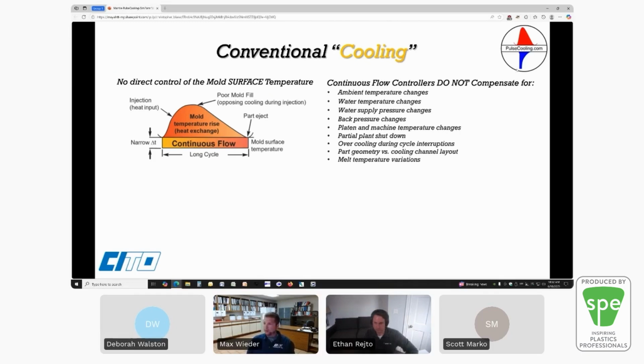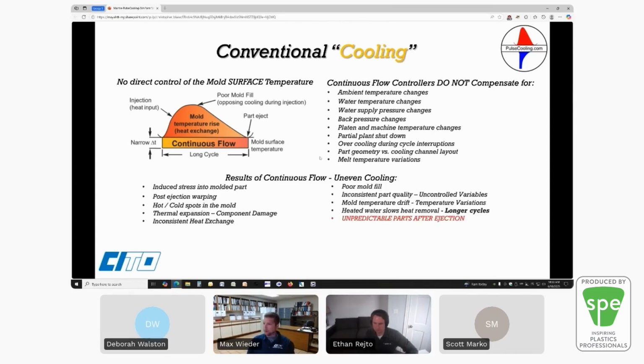The two biggest issues that we see is you have a very narrow delta T window here, which results in a slow heat transfer. You're trying to remove heat from your process with warm water. Cooling with warm water just does not make sense. The second issue is there's no direct control of the heat exchange on the molding surface itself. Both of these together result in longer cycle times and unpredictable parts after ejection.